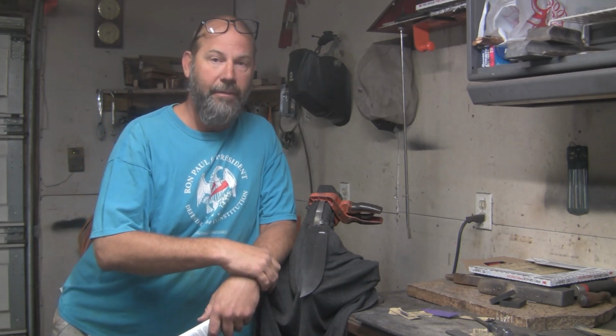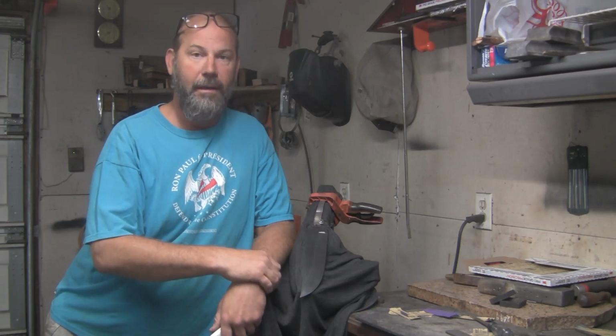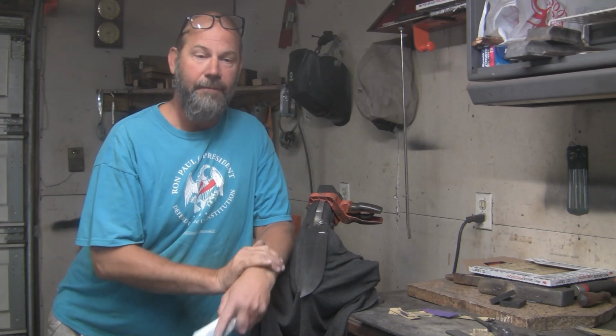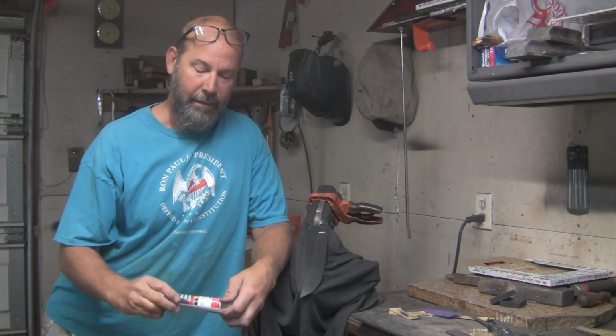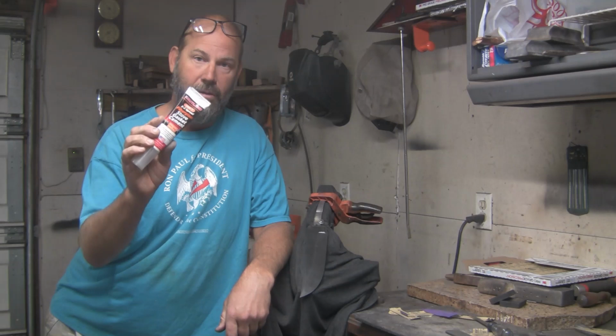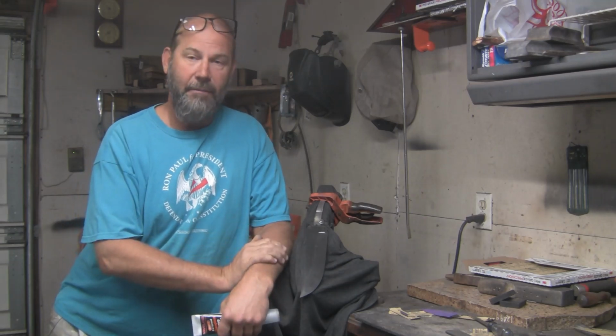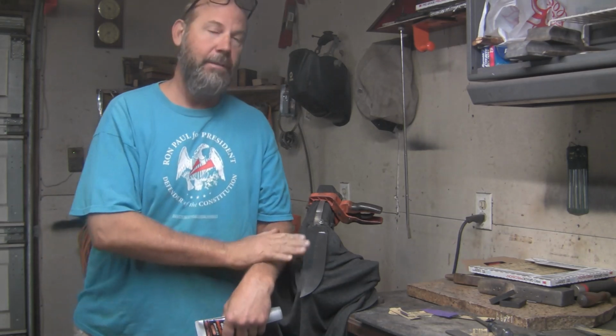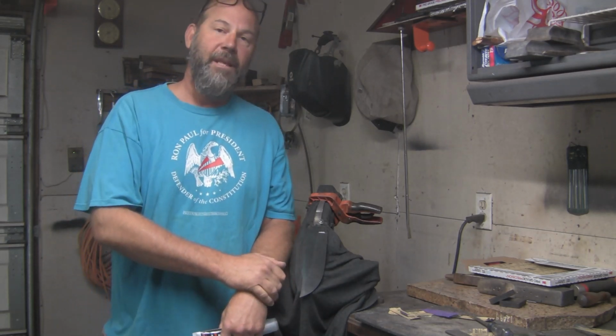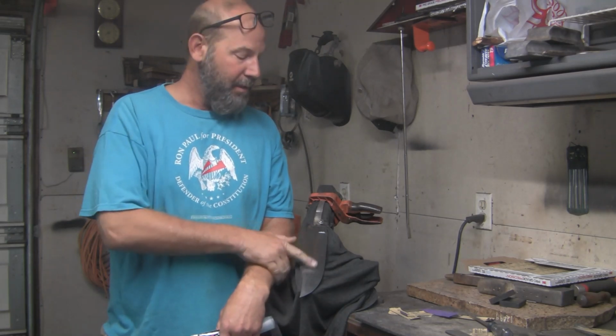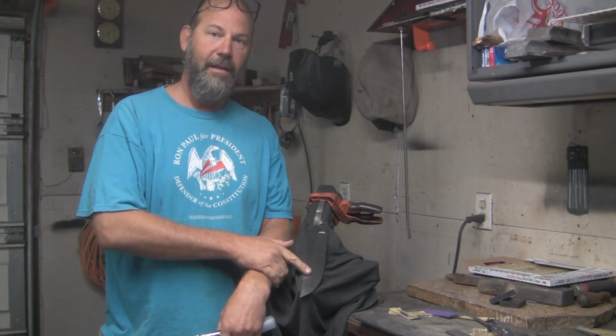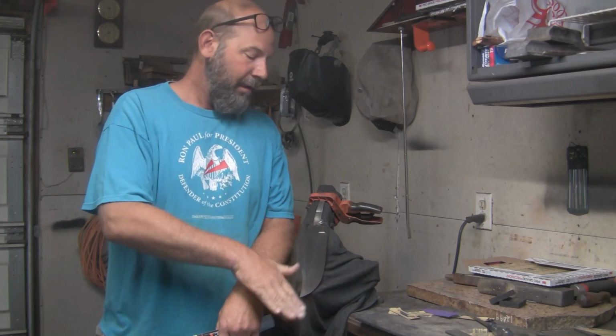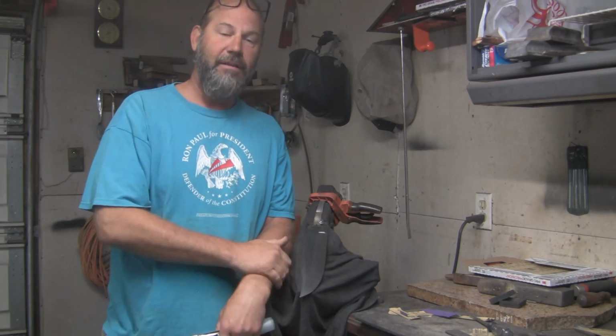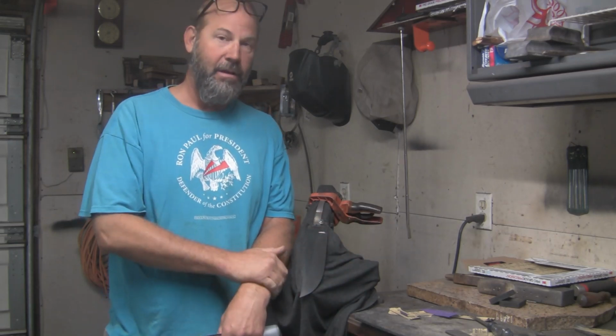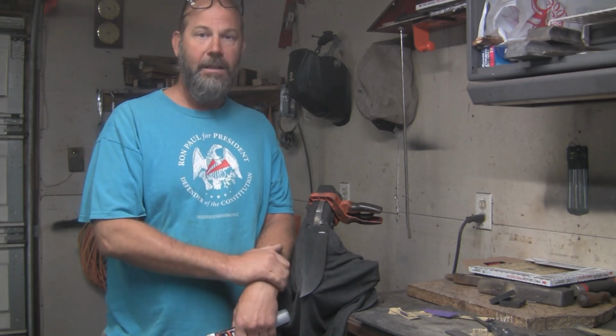One of the requirements of the build-off is that the heat treat needs to incorporate a hamon, which is basically just a differential hardening on, say, a mono steel. And that's what we're going to do. I'm going to use this stove cement to achieve that. We're going to mix up the slurry, reduce it down with some water, mix up a thin coat of slurry, put it over the entire blade, and then come back and do a thicker coat up in the thicker portions of the flats on the blade. Sam Towns actually has a really good recent video on how to do hamon, so check that out. It's over on his channel. So I'm going to try to mimic something of the sort.